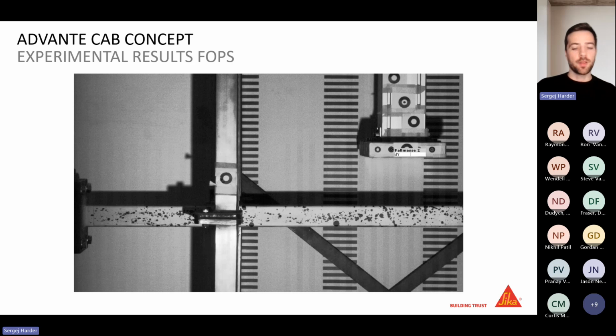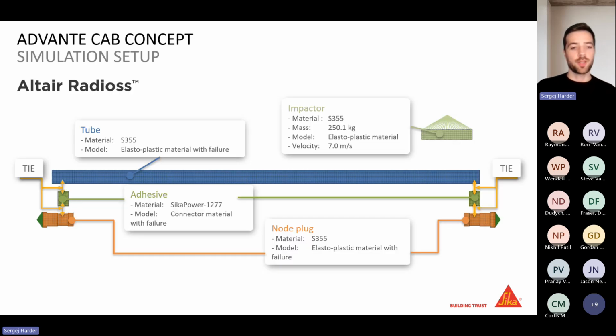So another important part for us was to show that we can also simulate this behavior, even this quite dynamic load case. So we set up a simulation with Radioss, which is an explicit solver. We had the modeling of the tube, obviously, which is also very important. There we had an elastoplastic material with failure, because we also saw some failure of the tube on the connection part. The adhesive is modeled by a connector material. You will often see cohesive zone elements in that regard. So this is, you could say, a numerically very effective way to model adhesives.